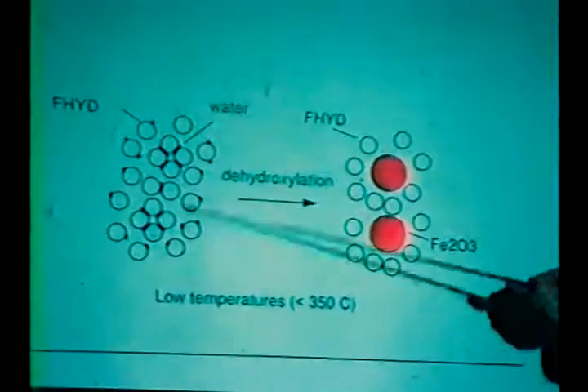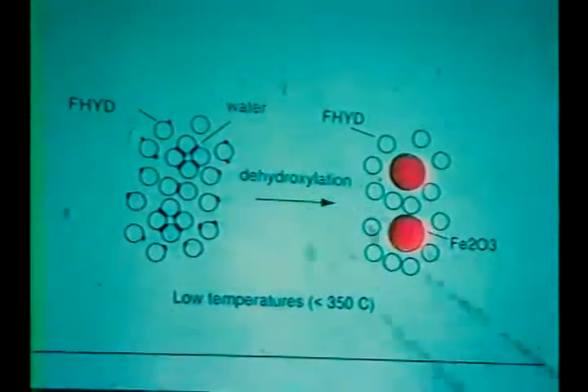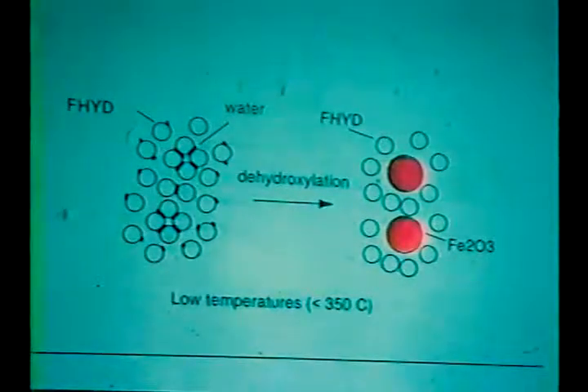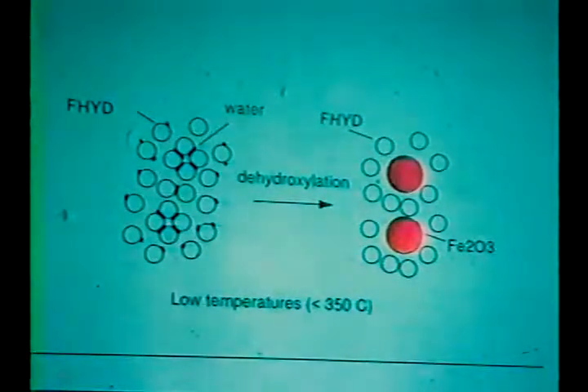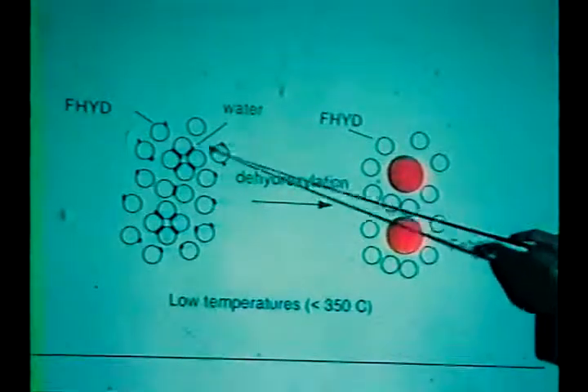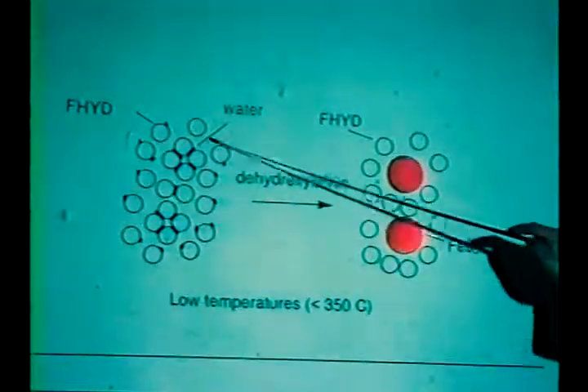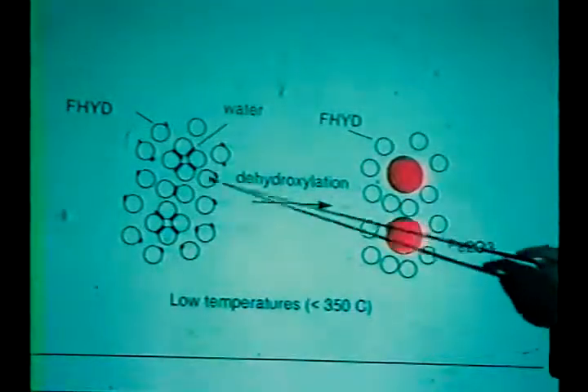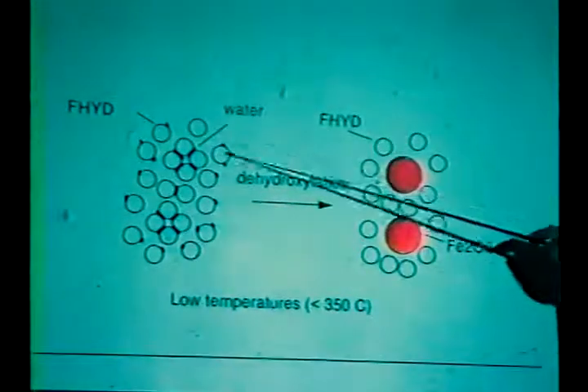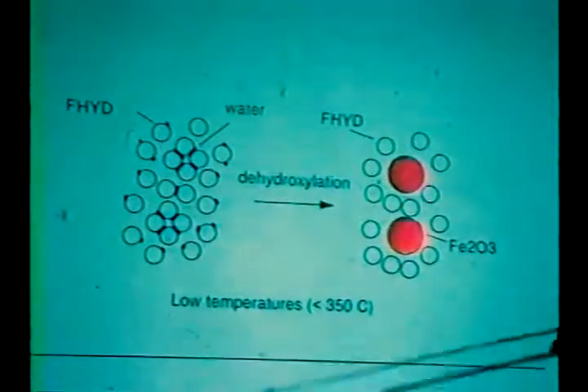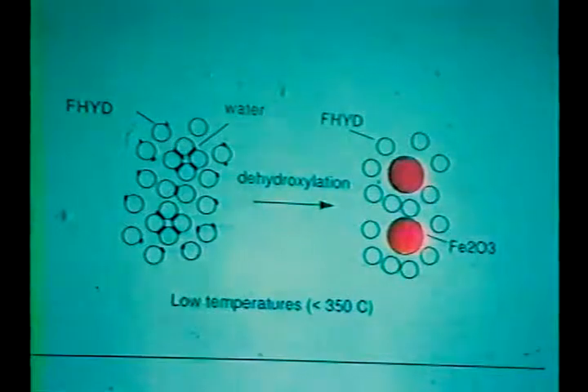It is very easy to prove whether this explanation is correct. If we have two samples, one dried, and one we purposely expose to air for 10 days, we expect the air-exposed sample will have more water molecules absorbed at the surface. Then we anneal both samples in the same condition and look at the TEM picture.